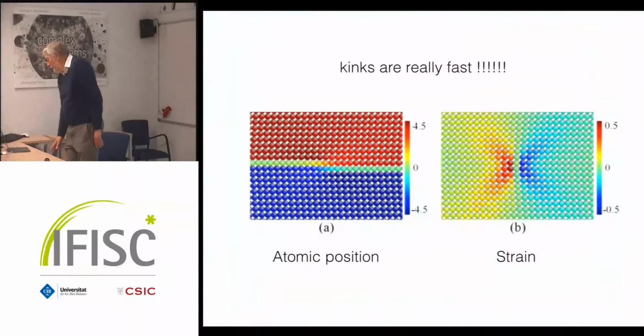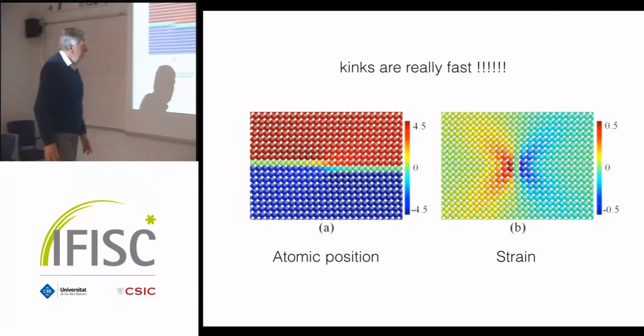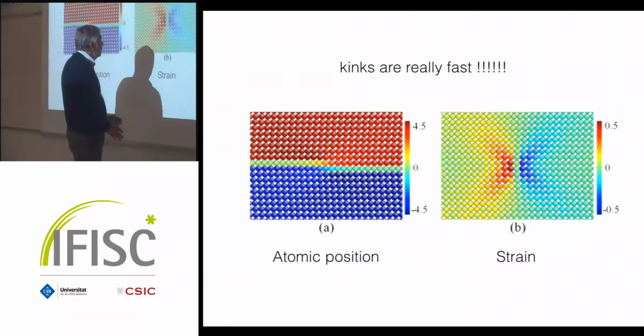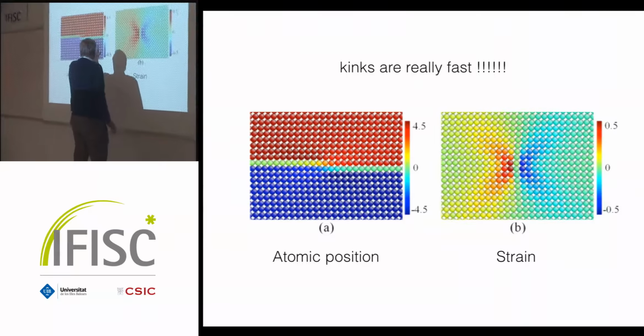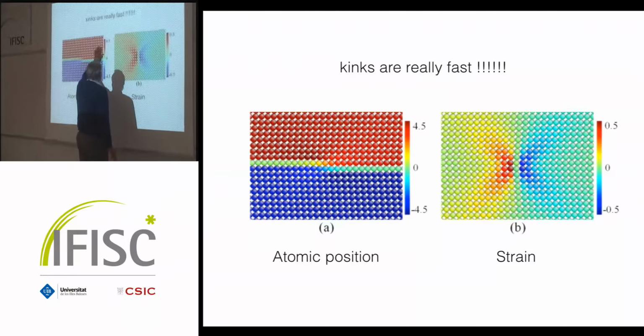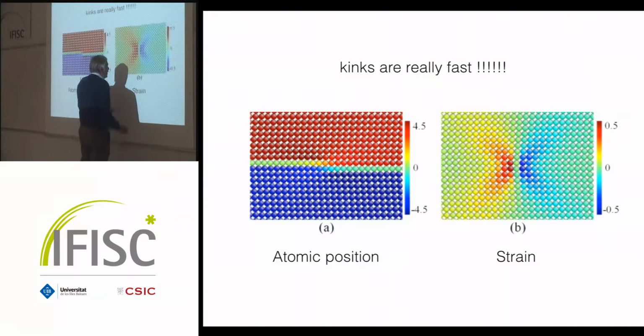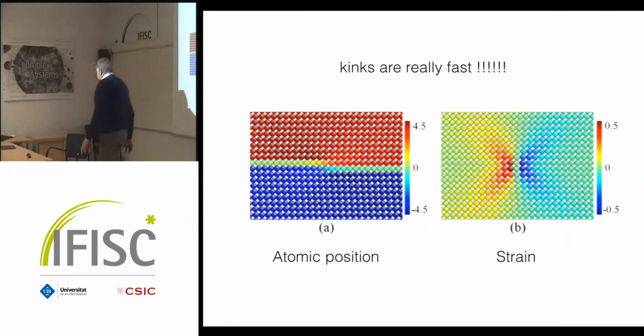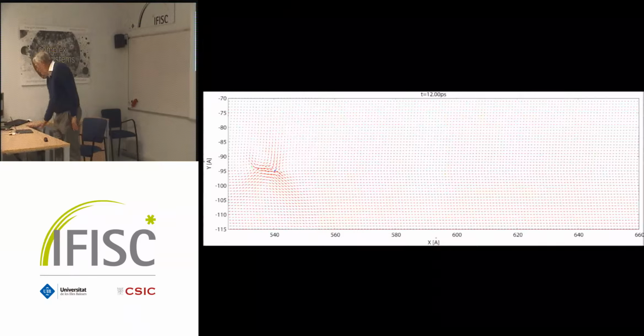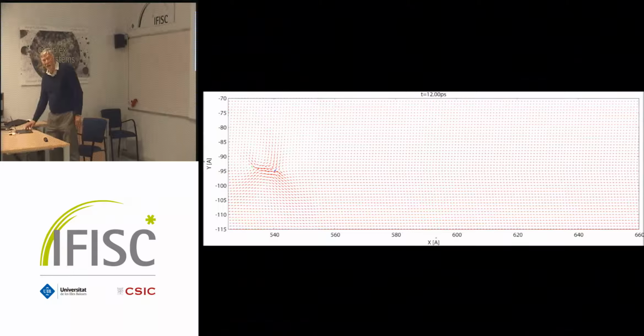Okay. So the last one I want to show is what happens if you have a simple situation where the strain is running everything. So you have one interface shear to the right, interface shear to the left, and this one gives you the strain. Then the question is are these atomic positions stable or are they unstable? And here you can see already the Eshelby deformation cloud which is there. So the question is how do they change? And the change is then of course by vortices. And here you can see the vortex.